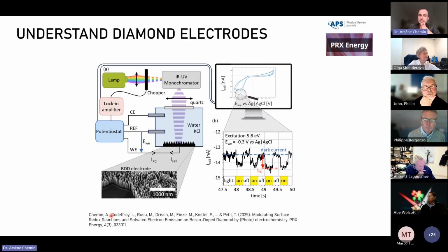That's a measurement I developed in Berlin during my postdoc, where we have a light that we shine through a monochromator, and then we shine the diamond electrode inside an electrochemical cell. And because the light is chopped, we can run a classical CV curve, but with the chopped light on top of it. That will give you the electrochemical behavior of the diamond here. But if you zoom in, you can see fluctuation in the current corresponding to the dark current, and on top of it, the photocurrent, which is triggered by the light.